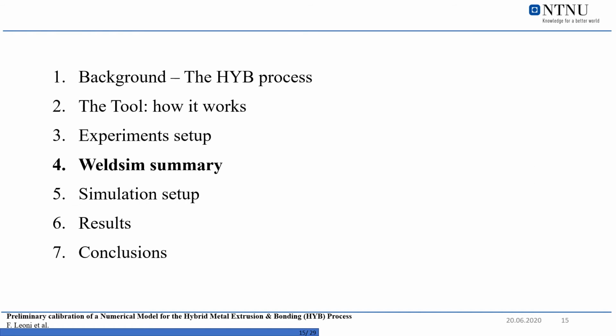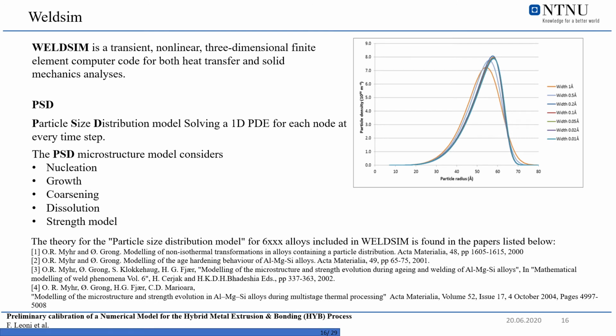Let's talk now about the WeldSim code. WeldSim is basically a transient, nonlinear, three-dimensional, finite element computer code for both heat transfer and solid mechanics analysis. The software has been developed with a particle size distribution model inside that is capable of predicting the microstructure evolution subsequent to a thermal history, which keeps track of the nucleation, growth, coarsening, dissolution, and so it is capable of predicting the strength evolution of the material.